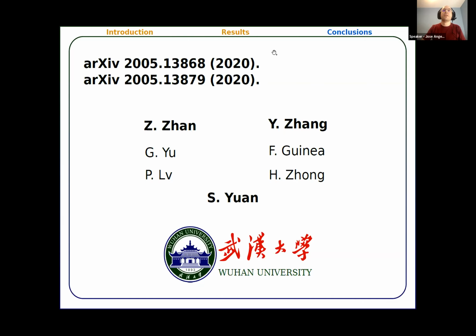So he's asking me if the model includes lattice relaxation. Right. The answer is no. The long answer is we have just done the calculations. It doesn't affect the flat bands itself, but it does affect the localization of the states, sorry. So it's actually quite important. And we have done the relaxations taking into account freestanding, twisted bilayer molybdenum disulfide, and the system on top of a boron nitride substrate.